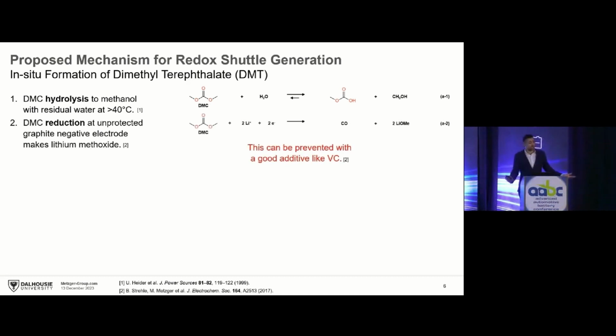And then another reaction that can happen is you can electrochemically reduce DMC. If that happens, you generate CO gas and a species called lithium methoxide. This happens if you do not have effective additives that passivate your negative electrode. If you have vinylene carbonate, for example, where you passivate your negative electrode first, then you would not have such a reaction. But in our control electrolyte, where we don't have that additive, we would form lithium methoxide.